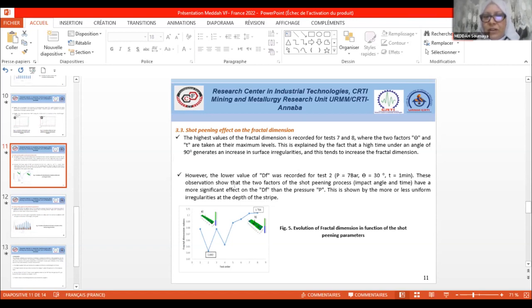However, the lowest value of fractal dimension was recorded for test number 2. This observation showed that the two factors of the shot peening process, impact angle and time, have a more significant effect on the fractal dimension than the pressure. This is shown by the more or less uniform irregularity at the depth of the stripe.